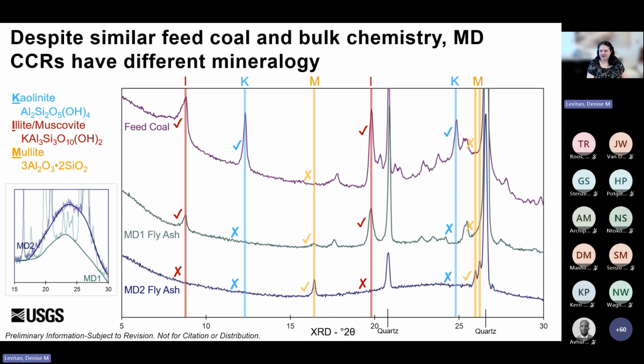And then finally, mullite, here in the orange M, is a mineral, an aluminosilicate mineral that forms from the thermal alteration of kaolinite, which again we saw in the coal, but not the ashes. And you can see there's no mullite in the original coal, peak here that you can't see.